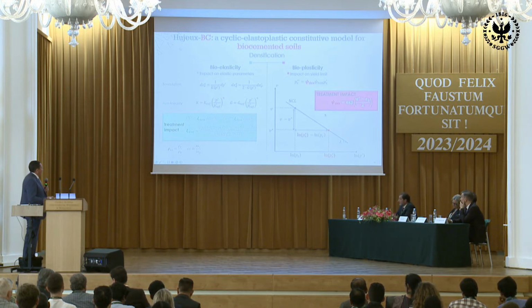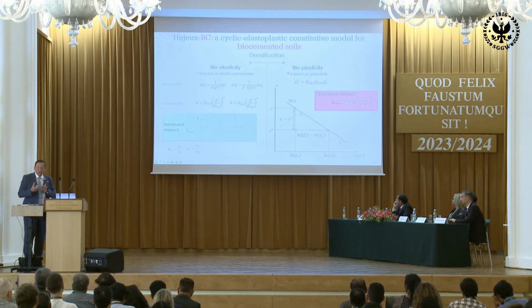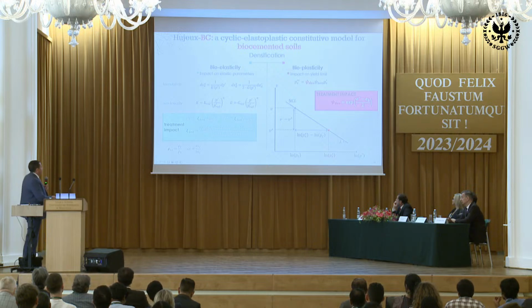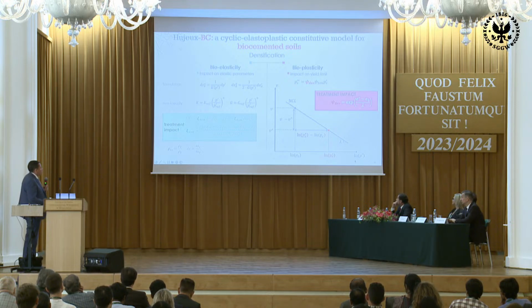For the bioplasticity part, this precipitation around the grains is reducing the volume. So basically, we represent a reduction of the volume, and if you reduce the volume, this is the normally consolidated line, so you are changing your pre-consolidation stress.